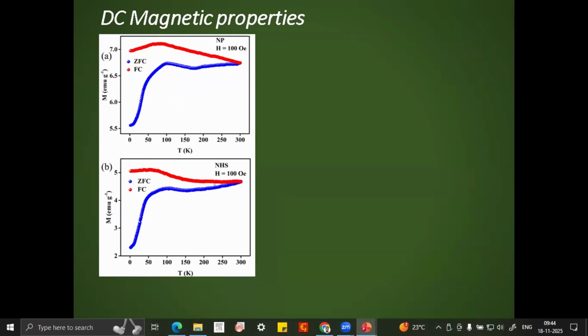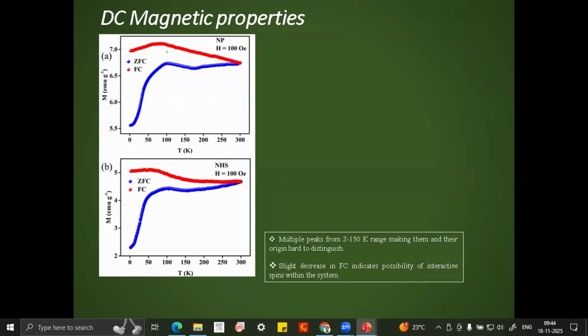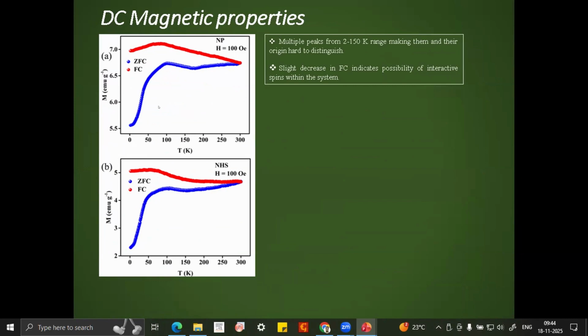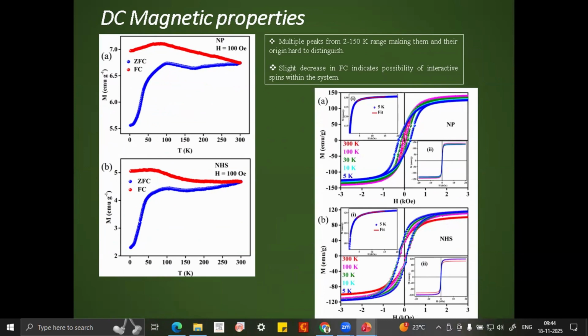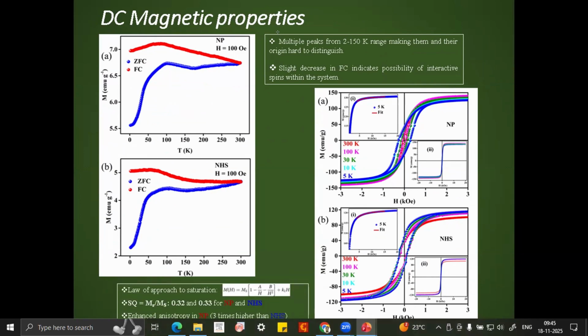With this visualization of my samples, I move on to the DC magnetic properties. This is for the nanoparticle, and this is for nanohollow spheres. The blue one is the zero field cool magnetization curve, and the red one is the field cool magnetization curve. From 2 to 150 Kelvin, there are a lot of peaks, making their origin hard to distinguish. So we also carried out magnetic hysteresis measurements, and the curves are fitted with the law of approach to saturation for both systems. This is for particle, this is for hollow sphere. From the fitting, we have 3 times higher anisotropy in nanoparticle than in nanoholosphere. This is the first indication that higher anisotropy may give a broad distribution of relaxation time that can lead to superparamagnetic nature.